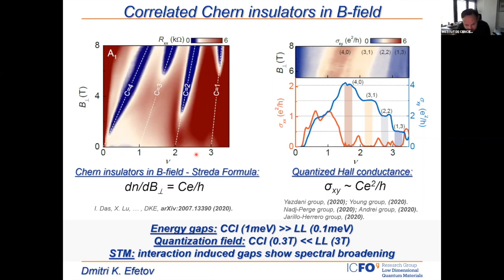And basically, the reason we also distinguish these states from just Landau level quantization is because we can also extract the energy gaps in this problem. And usually the energy gaps are an order of magnitude larger than for typical Landau levels. Also, the quantization fields are usually an order of magnitude lower. And I will show in a second that we also observe these states at zero field.